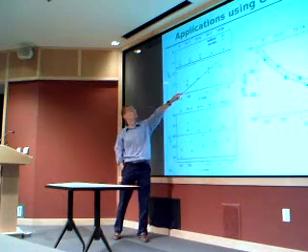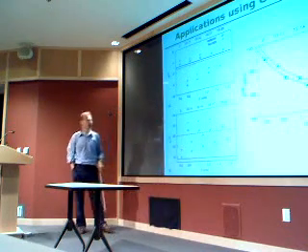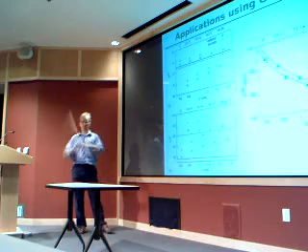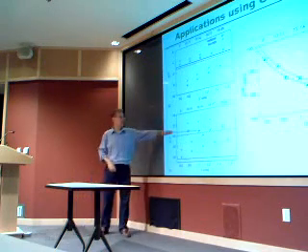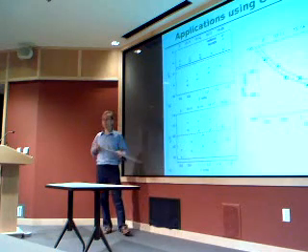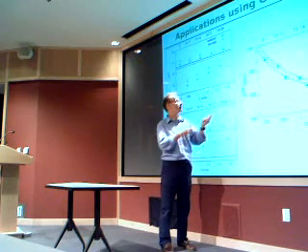And so, as a function of tube radius, they converge. And these two values they have from tight binding calculations for finite radius or graphene, so single layer nanotubes, and the same here. So if you would go to very large values, you would probably approach the tight binding value. So in principle, one can use the tight binding to get the susceptibility. And then for the chemical shift, one has to do the electron structure explicitly.